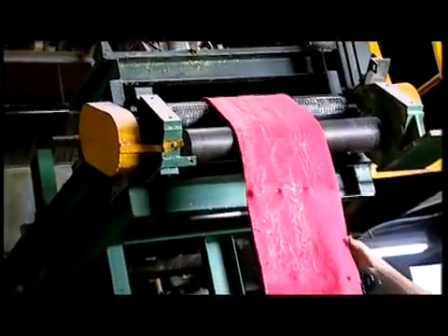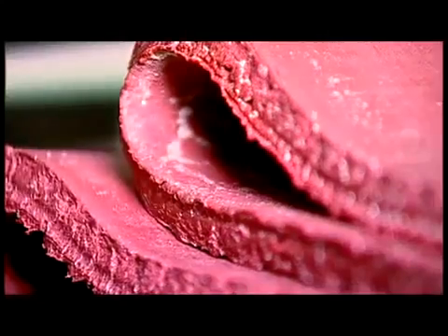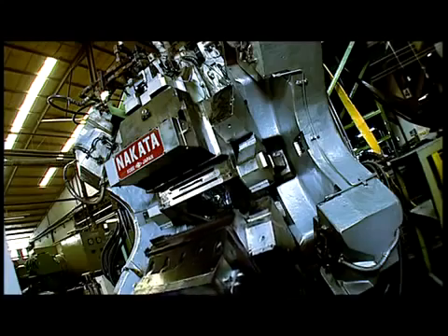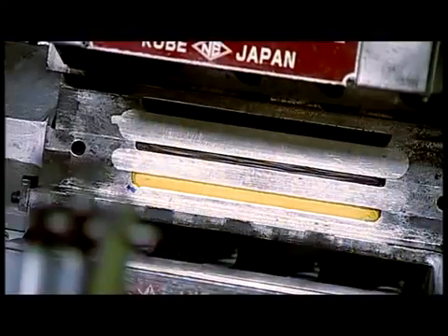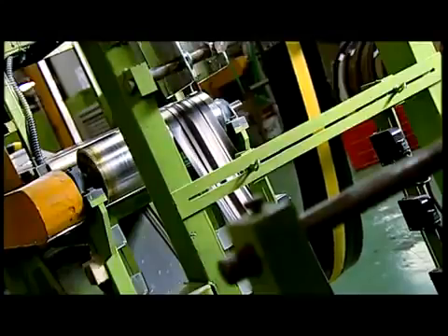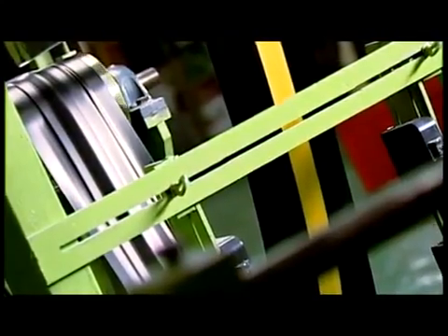The base mixes are rolled out into thick slabs called skins and temporarily stored before subsequent processing. The extruder combines different rubber mixtures under enormous pressure. A triplex extruder can combine 3 rubber mixtures, for example, center tread, shoulders, and sidewalls. A unique endless strip is produced for each kind of tire, cooled, checked for regular weight, and laid up in rolls.